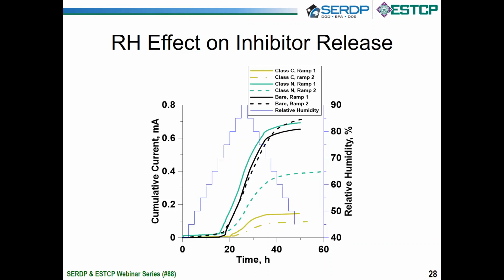However, if you run a second cycle, different things start to happen. So this dash curve is the bare. You see that there's really not much of an effect. As we move to the chromated coating system, you can see again that even during the second cycle of wetting and drying, we have a big knockdown factor in corrosion. In fact, it even looks better than the first cycle. And then as the non-chrome folks, you see that here you do get a knockdown factor.